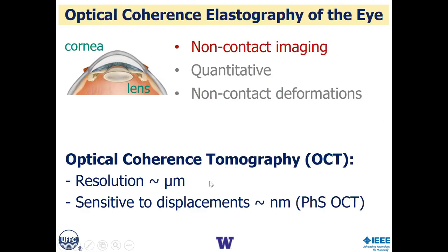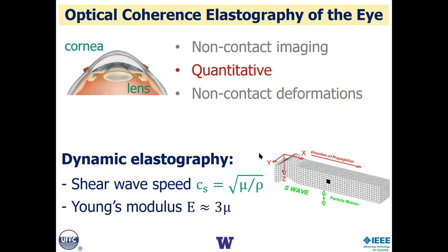Okay, how do we do non-contact imaging? That was easy. Two labs down from us in our department is one of the world's experts in phase-sensitive optical coherence tomography, Ruikang Wang, Ricky Wang. And so we talked to him about leveraging his systems, which are real-time 4D, so real-time three-dimensional imaging systems, optical systems that have resolutions in the microns, typically 10 to 20 micron scale optical resolution, but they're sensitive to displacements which are on the order of a nanometer or less. So very, very highly sensitive systems for looking at displacements, deformations. Second, quantitation. Our approach to quantitation is to use dynamic elastography.